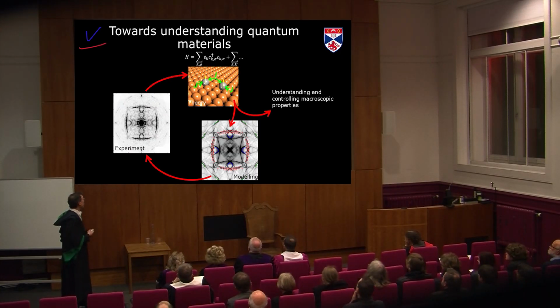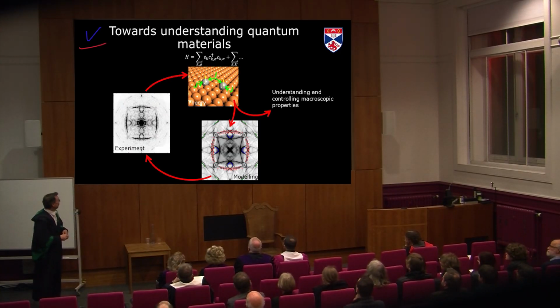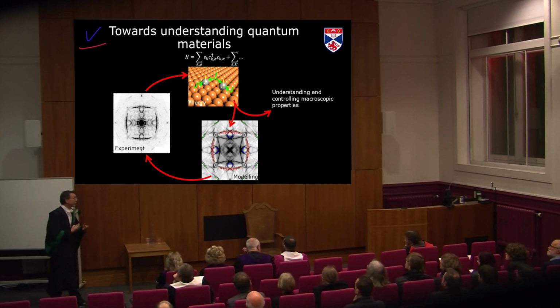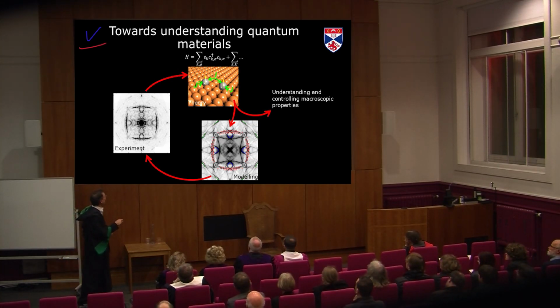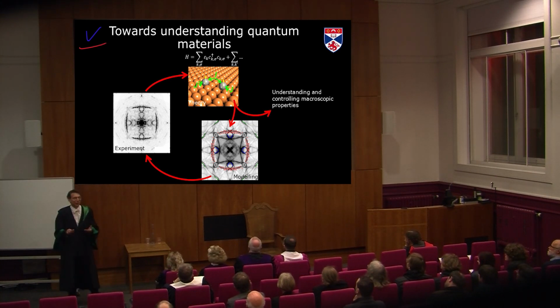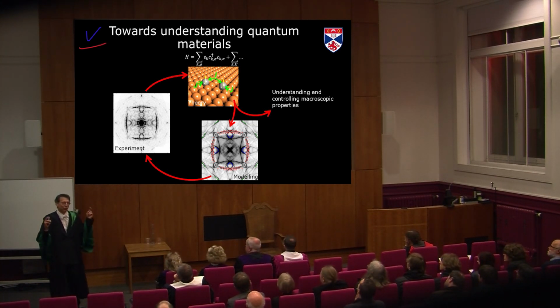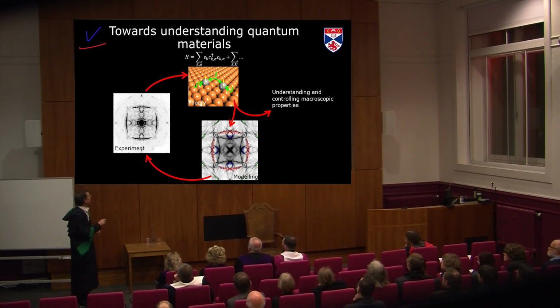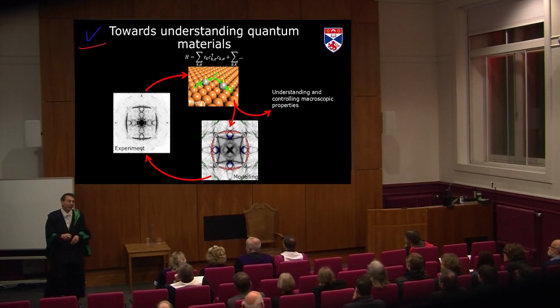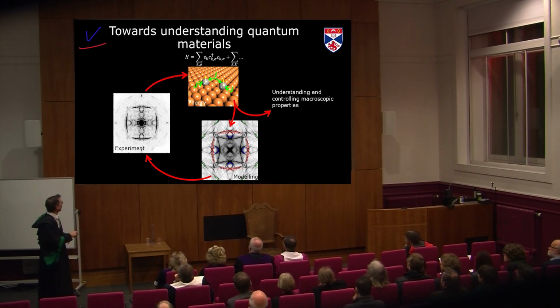And now what we do when we try to analyze that is we typically do our experiments where we get these patterns in what we call Fourier space, but then we try to come up with a model. We come up with a Hamiltonian. That's, if you like, the world formula for our materials. So we try to come up with a model which explains the behavior, and then we do a calculation to calculate how these patterns would look like based on the model, and compare that again with the experiment. And then typically iteratively improve our model until we think it gives a good description.